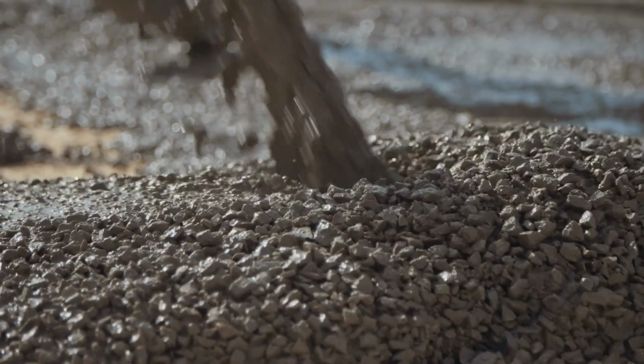During the hot mixing process, the lime clasts develop a characteristically brittle nanoparticle structure, creating an easily fractured and reactive calcium store within the concrete structure. As a concrete construction slowly aged and tiny cracks started to form within the concrete, the cracks would preferentially travel through the weaker, high surface area lime clasts.